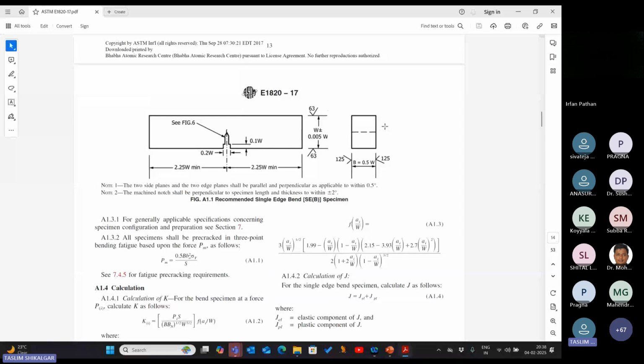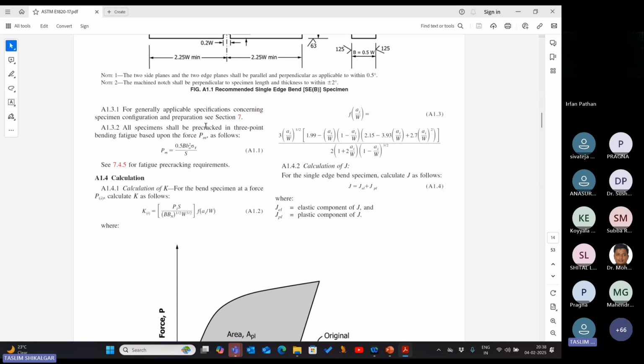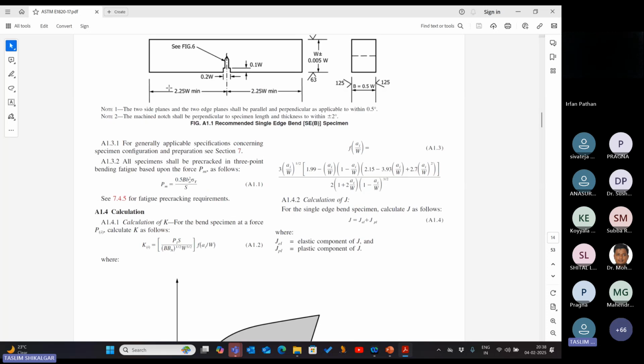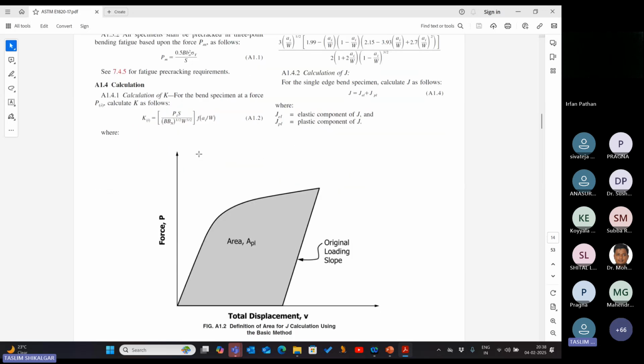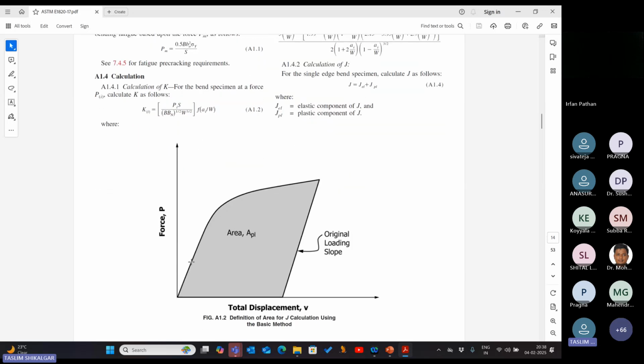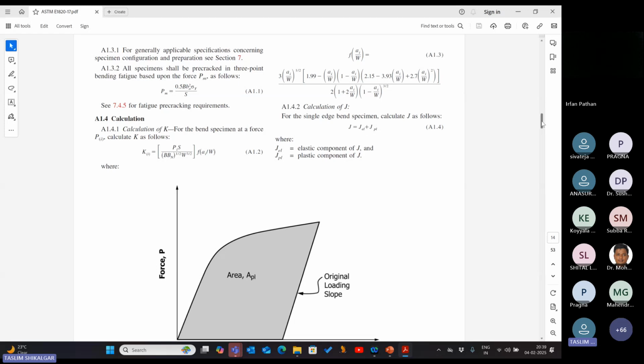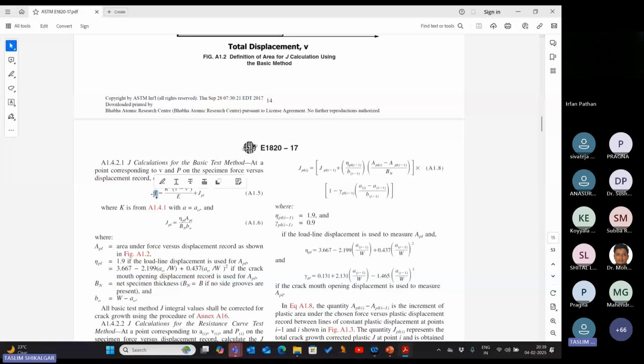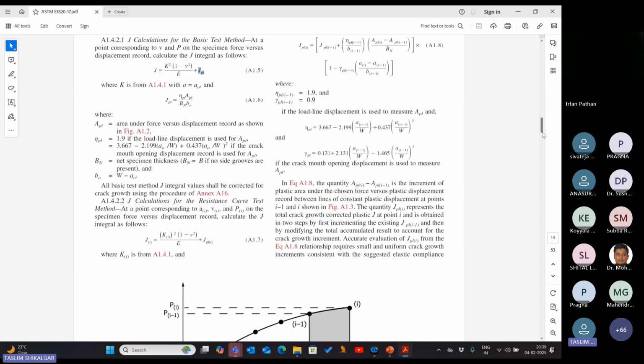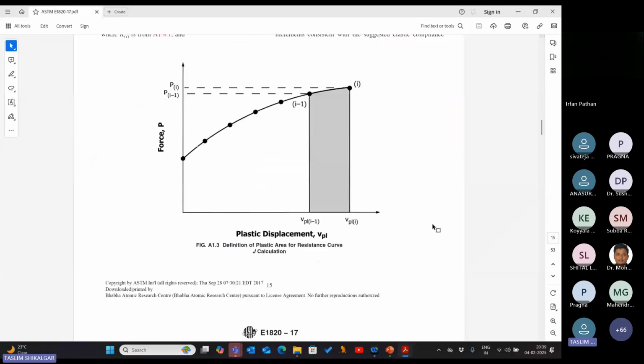Here, this is the 3-point bending specimen. These types of specimens are also recommended to get the fracture properties. They developed some empirical correlations to find the maximum load as a function of the yield stress, where S is the distance between the supports, and B is the thickness and width of the specimens. From these specimens we get the force versus displacement diagram, and from this diagram they calculate the J elastic and J plastic. This part is the J elastic and this part is the J plastic. J plastic is a function of the area under the curve. With the help of this J plastic, they generate these types of curves, like J-R curves.